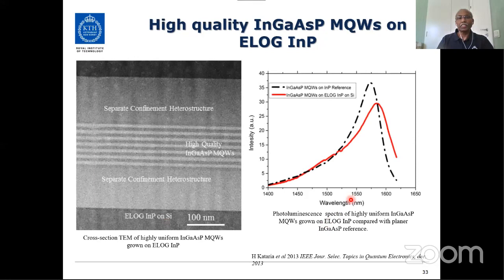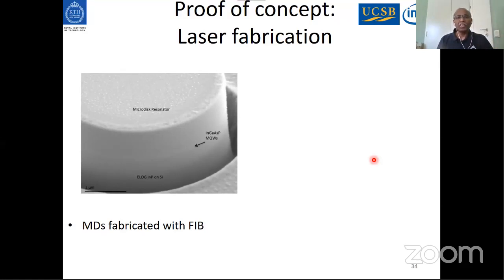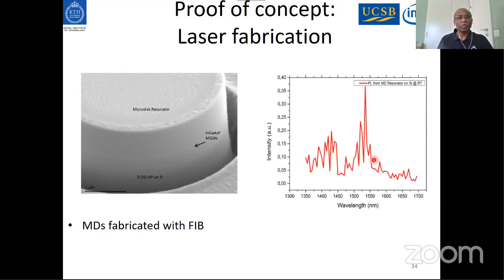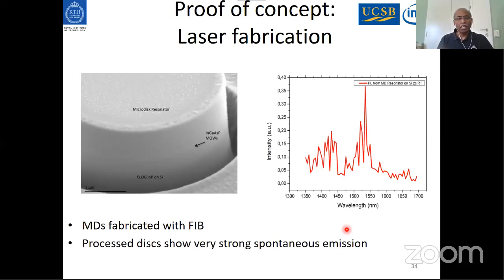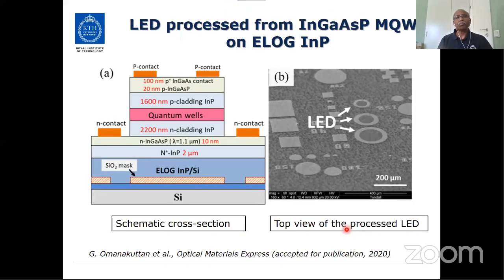And here is the photoluminescence spectrum for the reference, and here is for the multi-quantum well on indium phosphide on silicon. We get almost 80 to 90% of the intensity with respect to the reference sample. But unfortunately, we are not able to make a device on that for several reasons. For example, we tried to make micro disc lasers, and we got very, very strong spontaneous emission, but we have not obtained the laser yet. Recently, we tried to make lasers, but the laser did not work. On the other hand, we tried to see if it can work as an LED, and in fact, it worked.